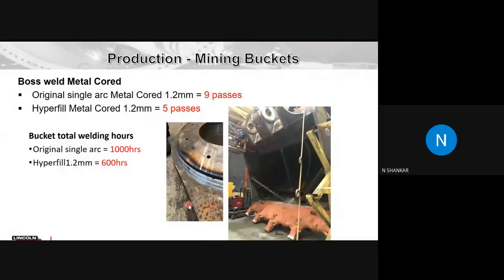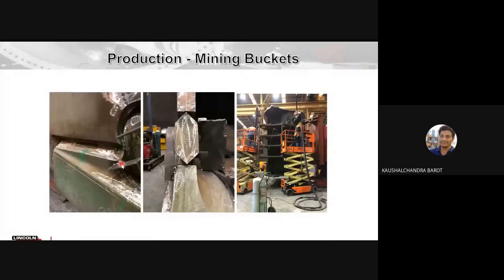Some of the examples, here's the hybrid process that's used for mining buckets. Earlier, it was done with 9 passes using one metal-cored 1.2 mm wire. By implementing the hybrid process, they were able to do it in 5 passes. So they reduced 4 passes, and the original arcing time or the welding time came down from 1,000 hours to 600. This is a huge mining bucket. 1,000 hours of welding was reduced to 600 hours basically. 40% reduction, but 400 hours of reduction.